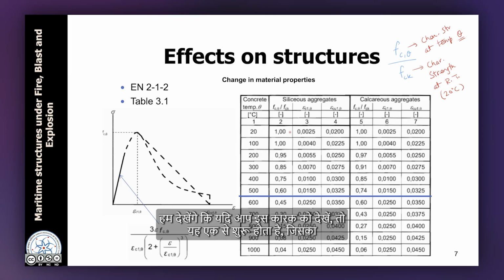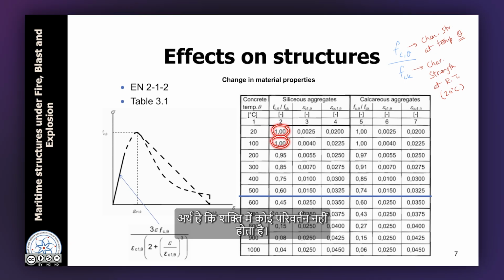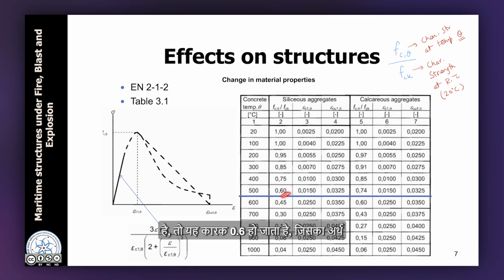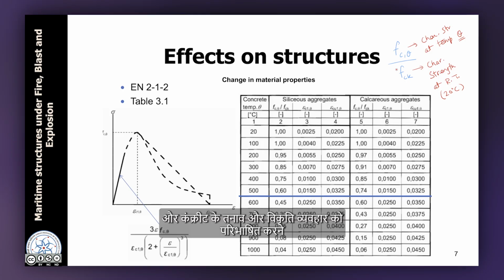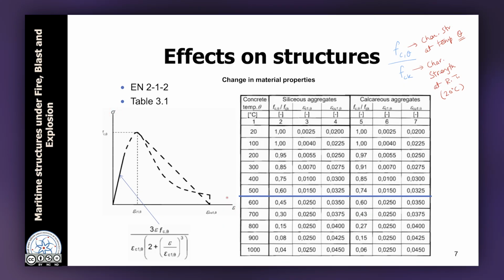We will notice that this factor starts out at 1, which means no change in strength, but when we reach 500 degrees Celsius, the factor becomes 0.6, which means somewhere between 500 to 600, the concrete will lose half of its strength. So that is this ratio. And for defining the stress and strain behavior of concrete, we draw the stress versus strain, and this has been parameterized with Fc theta and two levels of strains. The degradation in the strain is also given, and for concrete it depends on the kind of aggregate also. So this is for siliceous aggregate, this is for calcareous aggregates.